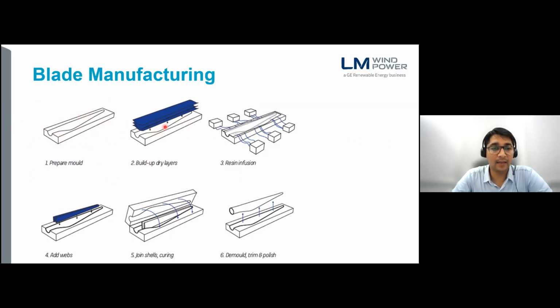We lay up dry fiber glass materials, so glass because glass is most widely used, but other fiber materials too, into the blade cross section, ensure its conformity to the cross sectional shape, and then cover it by vacuum foil, seal it from all the sides, and apply a vacuum pressure of about 1 bar, and then inject resin through resin injection machines and the pipes, and also the vacuum enables the resin injection machine to put resin into the blade cross section. Once this part is cured based on what kind of resin system is used, we add the shear webs that I showed you in the last slide